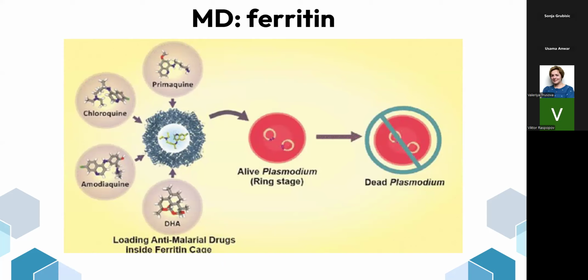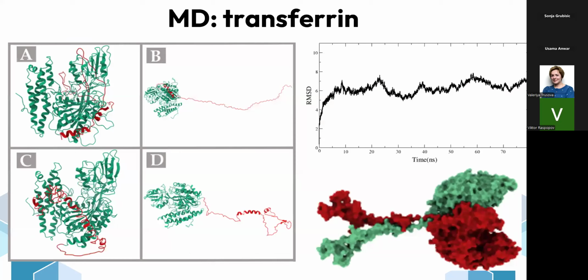So these studies demonstrated that drugs like anti-malarial drugs can be readily incorporated into ferritin without disrupting the native conformation of ferritin, while when the researchers incorporated antiviral drugs, the conformation of ferritin was broken, and this was selective binding of the drug molecules to the protein.